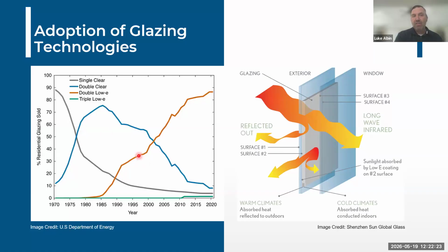Fast forward to the mid 90s, is really where the low E coatings took effect, and that's where we are today. Now, close to 90% is double low E coated windows. You'll see here a little line for triple low E, a little tick up, primarily driven, now there are some early adopters and those that find the value in putting a better window within their buildings, but driven by code. And that's where we see things. Going back to Keegan's previous slide, we're seeing not only the codes changing, but also the incentives are really robust enough to be able to pull in a much better high performing window.